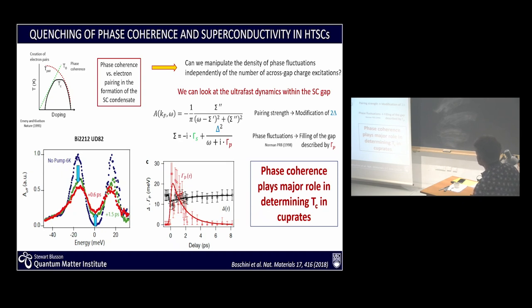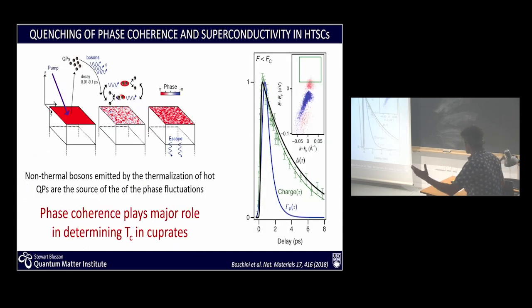And then we can plot in black the reduction of the gap, and you can see it's about a 10% reduction of the gap itself. Much of the action, as you can see visually, is in the gamma p, so the broadening of the spectral function in the superconducting state as you quench superconductivity. Now, this has been done, again, Luke has done much work in that direction, also using equilibrium photoemission. I'd like to stress how this is now done time resolved and is not a thermal effect.